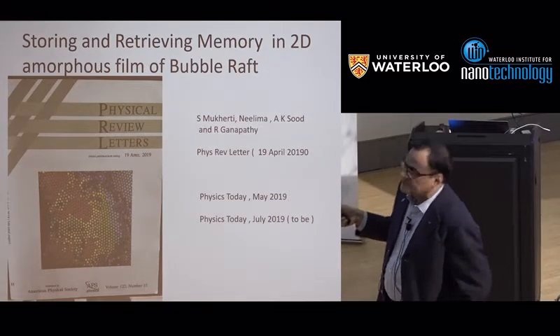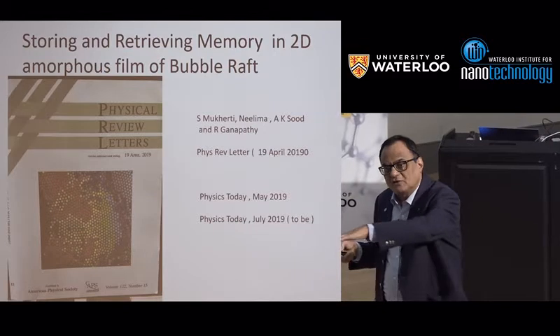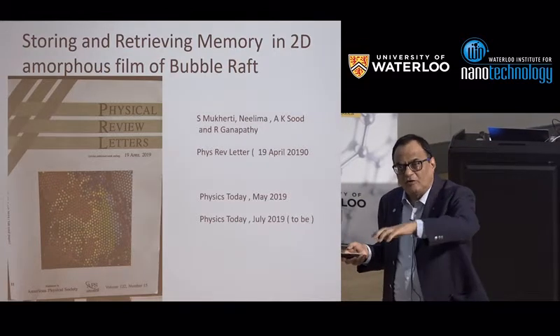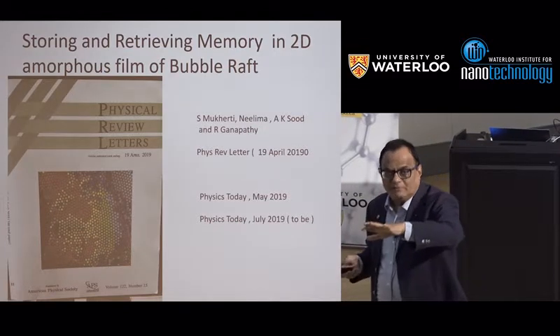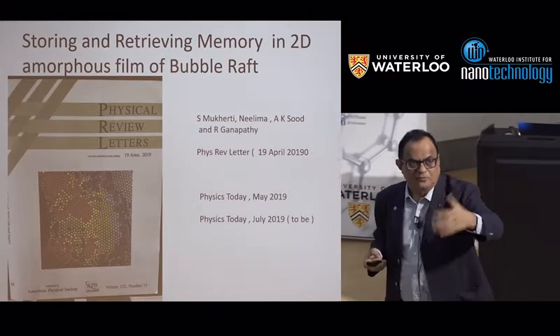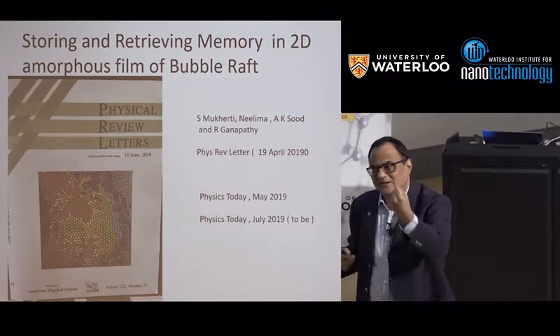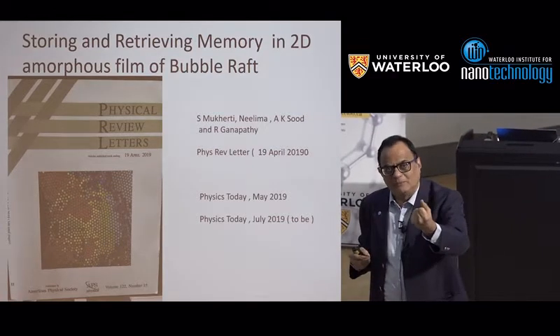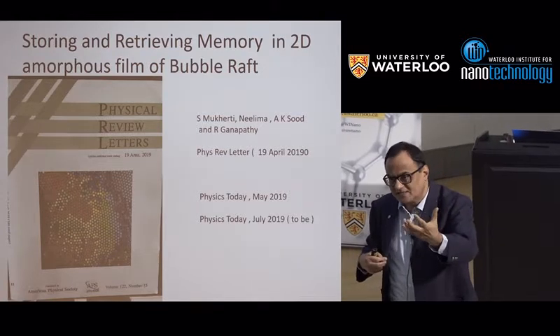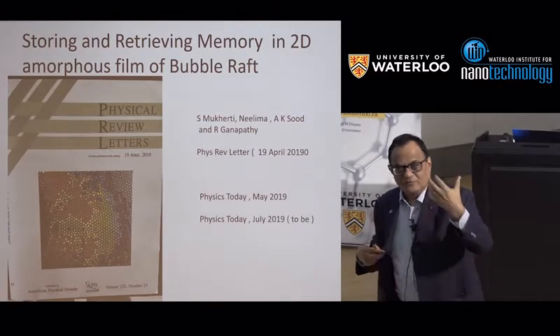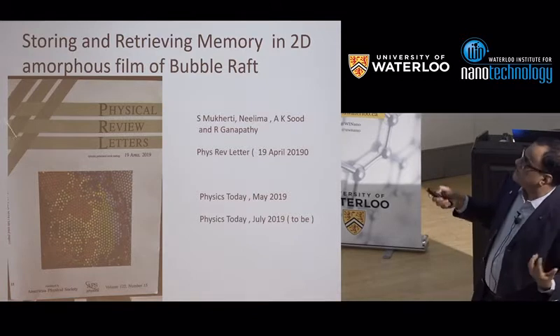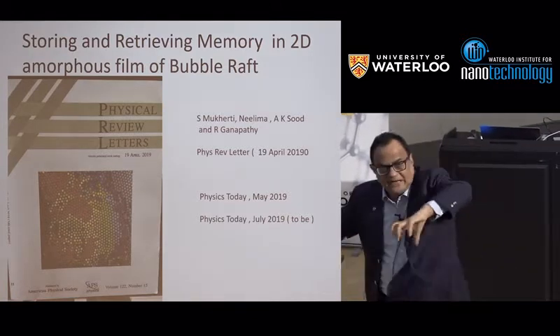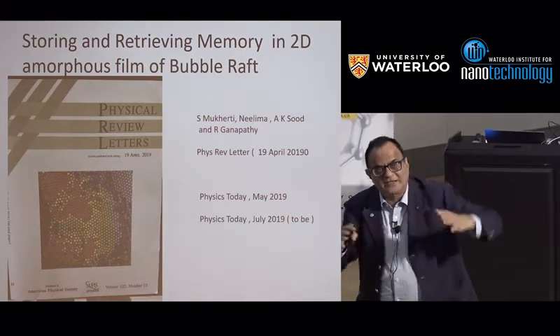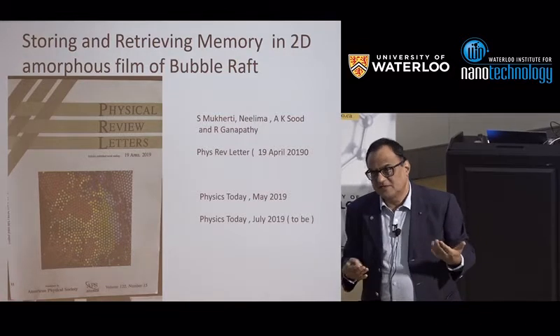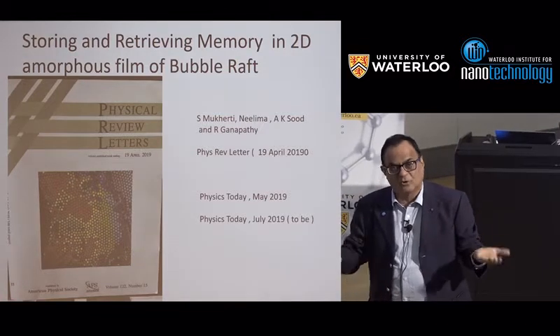So what we have done is, we form a two-dimensional colloidal glass of bubbles with soap bubbles, good old soap bubbles, but you have to practice for 6 months to get stable soap bubbles which can stay for about 20 hours without popping. If you get that correct, then we shear them with a plate and measure quantitatively their stress response. So they have a yield stress. It's like a colloidal glass.